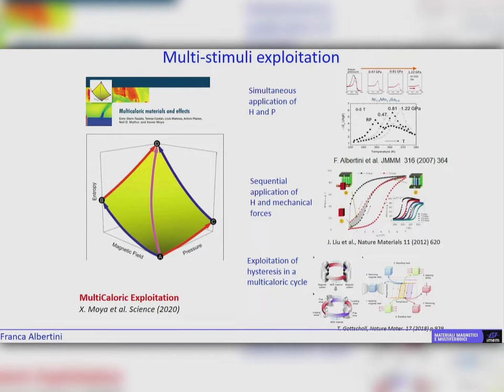More recently, multi-stimuli application on these materials has been proposed for multicaloric exploitation, which allows applying different external fields at the same time, that may be magnetic field and pressure. This application can be simultaneous or sequential, and they have been used to increase some of the multifunctional properties. For instance, the simultaneous application of field and pressure has increased the magnetocaloric effect. The sequential application can be used to reduce the hysteresis and fully exploit these materials, or also they can be exploited in a multicaloric and more efficient caloric cycle.